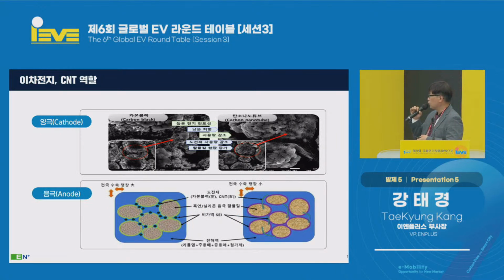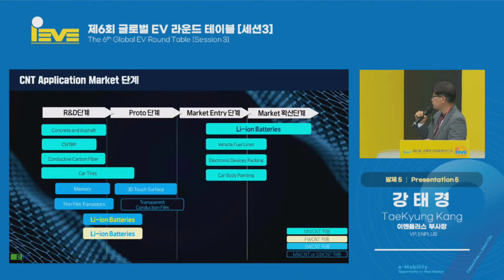And cathode and anode. For cathode, we have to use it to lower the resistance and reduce the usage rate. And whether the conductive material is metal or silicon, well, they all say they're the best. But off the record, I think compared to lithium metal, silicon is going to be used for 70%. We don't stick to single silicon material, but when we test with silicon, silicon expands a lot. And I'll get back to this later on.